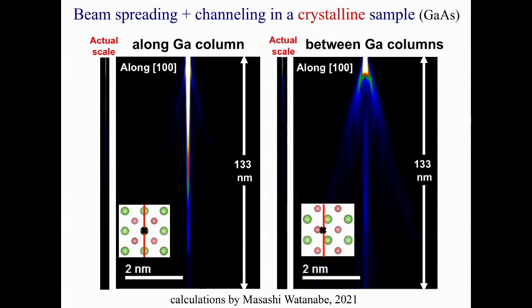Things are not so bad in a crystalline sample, provided the electron beam coincides exactly with an atomic column and is parallel to it, the situation shown here on the left. The positively charged atomic nuclei actually focus electrons down the atomic column. But if the probe is shifted just half an interatomic distance, or is not parallel to a crystal axis, then we have the situation on the right, which is more like the amorphous case. The only way to avoid beam spreading is to make the specimen extremely thin, which is not always possible.